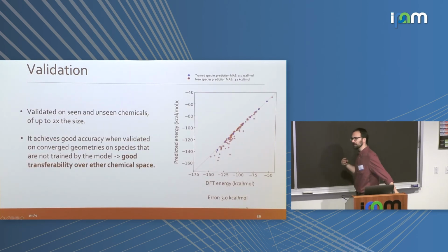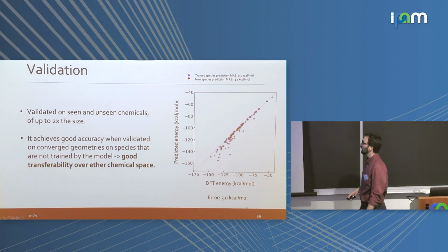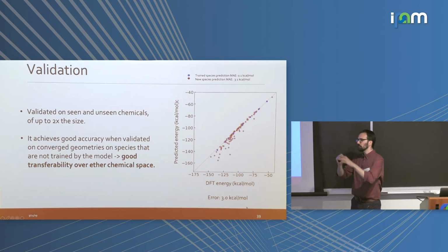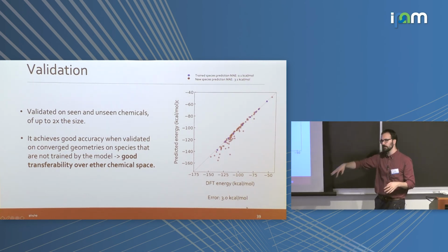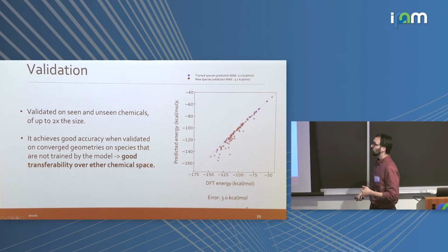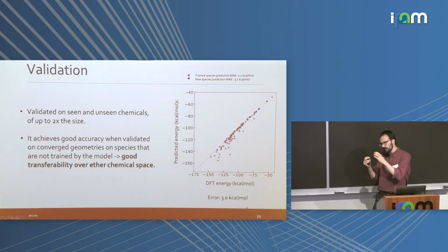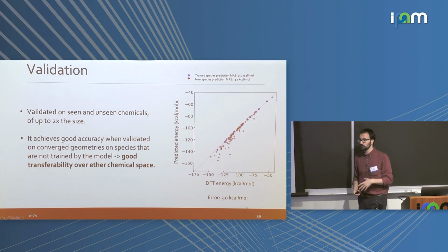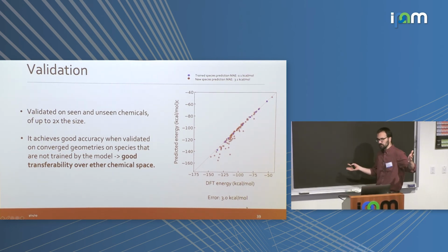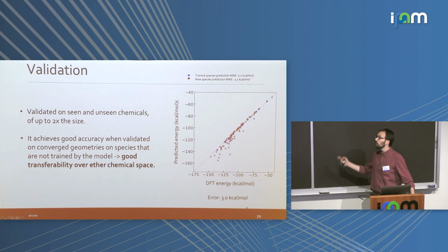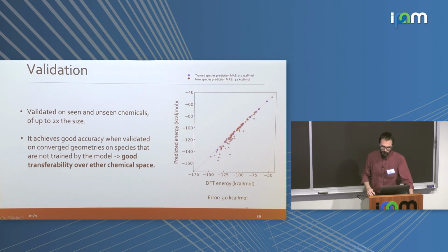So now that we're certain that these things hold and we can explore phase space, then it was not too challenging, right? We run molecular dynamics with the small molecule and the lithium. From time to time, we take frames and do gradient descent to see what is the minimum that they explore. We find all these minima for a bunch of chemistries, and then we compare the binding energy, the lithium binding energy, which is the thing we want to maximize, with the DFT, with the reference. And in general, it works pretty well. All the red ones are chemistries that were not in the training data of the potential. The chemical space transferability, I think we took for granted, but it looks like it works well. It's a very constrained chemical space. But the configurational space transferability was a little bit of a challenge.